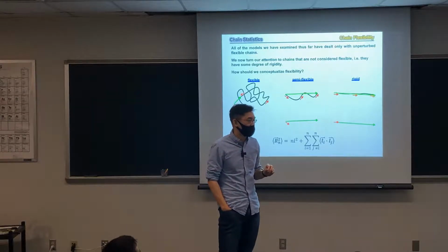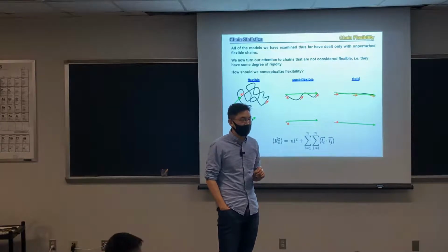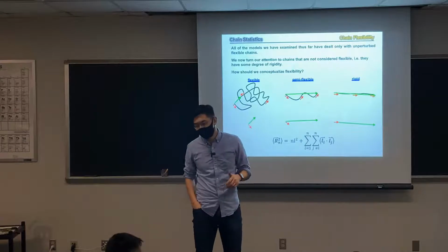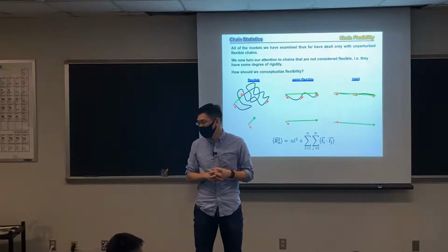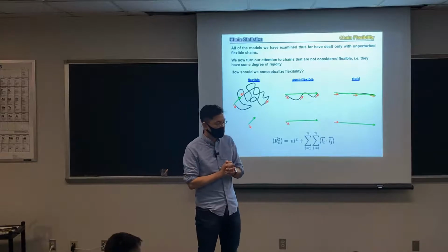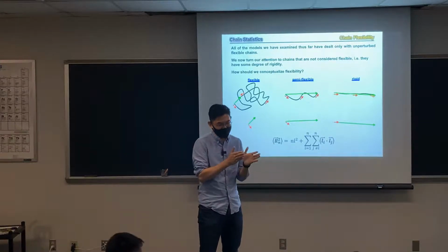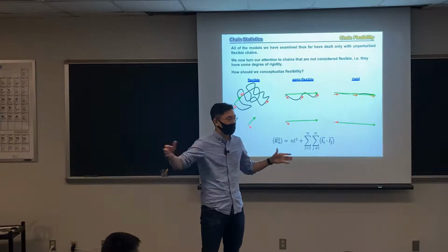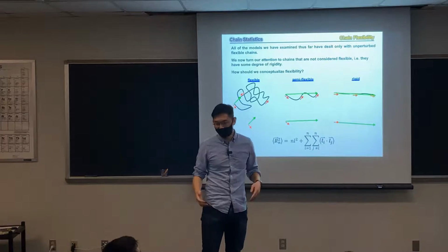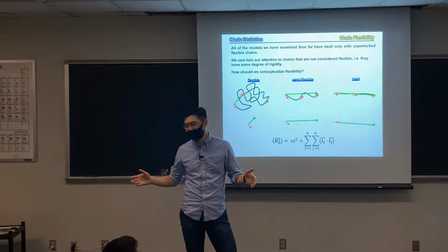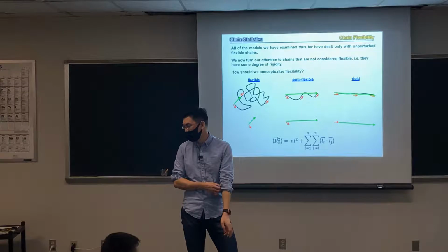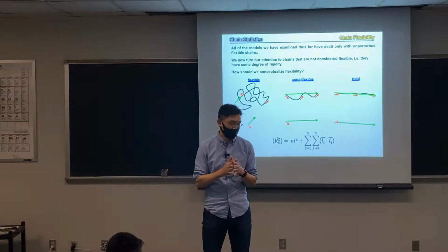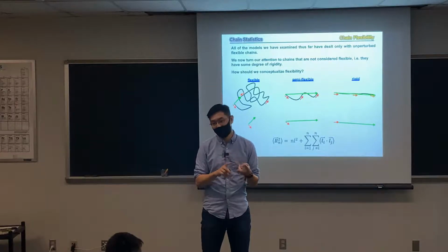They are regarded as rigid, and that structure has a persistence length typically on the order of close to 100 nanometers, okay? Or even higher in some cases. So DNA, if it's low molecular weight or shorter, is a rigid rod. But if you make very, very long DNA, it's like a kilometer-long stainless steel rod, it will still have a lot of flexibility, okay? So when you discuss flexibility, always understand it in the context of what LC and LP are.